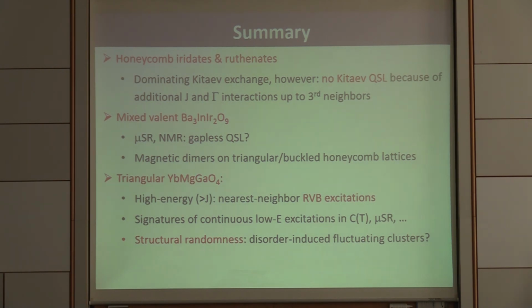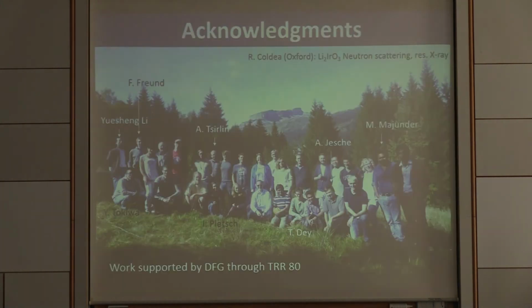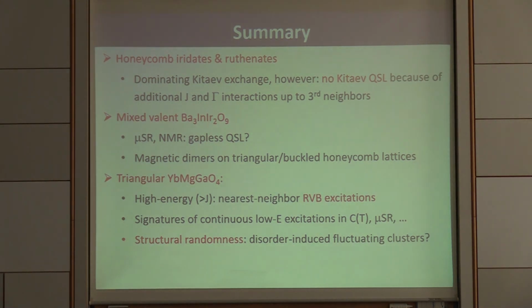So in the first part of the talk, I discussed honeycomb iridates and ruthenates. And I showed evidence for the importance of the Kitaev exchange, but in all these cases we have additional interactions like a third neighbor J and off-diagonal terms which drive us away from the Kitaev spin liquid. Then there is this new mixed valent iridate where we see indications for a gapless quantum spin liquid, but here we do not yet know whether we have to treat it in a triangular or a buckled honeycomb lattice or even a combination of both. And then there are these rare earth-based triangular magnets where we have at high energy the realization of nearest neighbor RVB excitations on a triangular lattice.